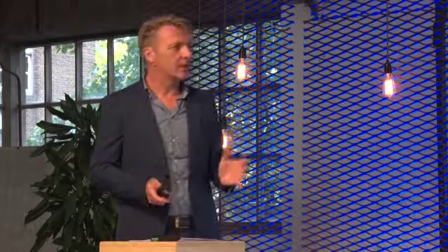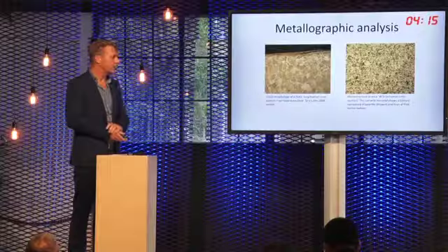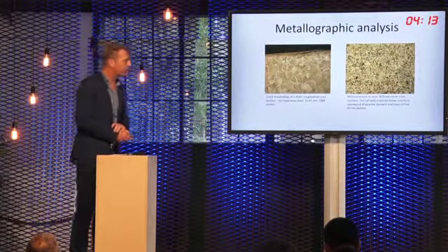The web area was 1.7 times more wearing than the head area, and I think that could also be the explanation for the absence of the cracks, because this is shifting it into the regime which is fully dominated by the wear.